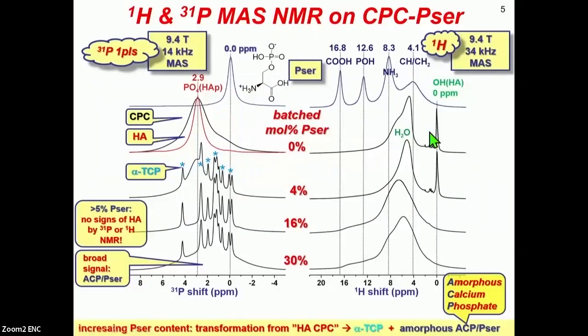So here you see phosphorus-31 and proton NMR spectra recorded from polycrystalline phosphoserine and then from cements with increasing phosphoserine contents. And in the cement without any phosphoserine, both NMR spectra are typical for disordered hydroxyapatite. Then if you take a look at the spectra from the cement with 4 mole% of phosphoserine, you can still see the apatite component. But there are also a set of very sharp NMR peaks forming, and they come from unreacted alpha TCP.